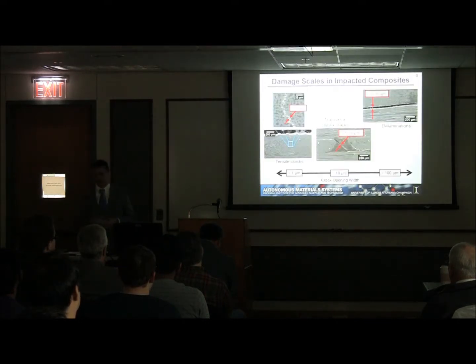So in this schematic here, we have a microcapsule embedded inside of a polymer system, and this microcapsule has a hard outer shell, liquid core on the inside. And as the material is damaged and a crack propagates through, the liquid is released and reacts with some sort of catalyst or some other chemical inside of the crack to heal the material back together. So if we consider the damage that actually occurs inside of a composite, it can range in size scale from roughly 1 micron in the case of tensile cracks, for instance, seen here, up to hundreds of microns if we have fabric separation, or what we call delaminations.